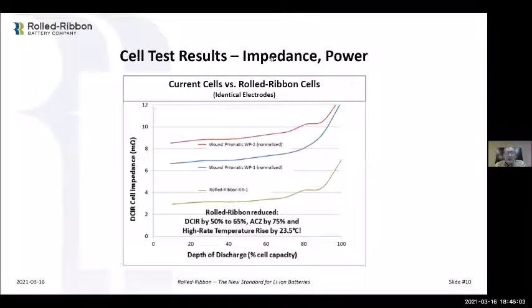So here's the test results comparing. What we did in this thing here, we actually did this for the military, had to do with some directed energy weapons. So we took a wound prismatic cell, a couple of them here to get a statistical area, and then we produced a roll ribbon cell. We made the cells identical electrochemical formulations. So these are the exact same electrodes. They were made on the same line, same machine, same time. One cell was wound as a prismatic, and the other one was wound as a rolled ribbon cell.